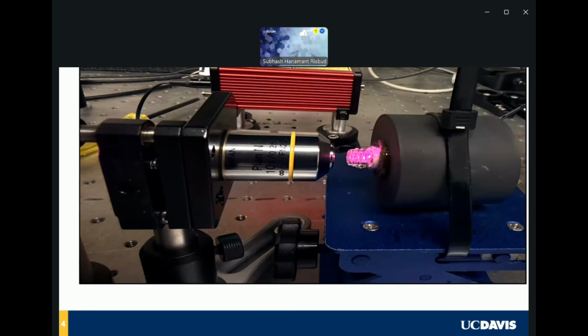The middle of it, you see turning glowing orange and yellow, is where the melting is happening. And then the glass that comes out of it is the result. And usually, in about 5 minutes at the most, the temperature reaches fairly high temperatures, as I mentioned. And so I'll tell you what that is. Here's a closer look at it.